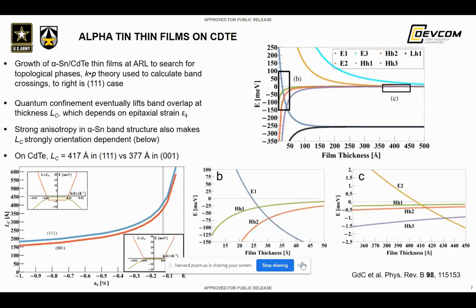So using this concept, George carried out the k.p theory calculation. He treated the alpha tin layer as a thin layer, which is quantum confined by the vacuum on one side and by the substrate on the backside of the material. And using quantum confinement arguments, you can show that you can lift the band gap as the thickness of the material is varied. And there's a critical thickness depending upon the strain, above which the material can go from a Dirac semi-metal to a 3D topological insulator.